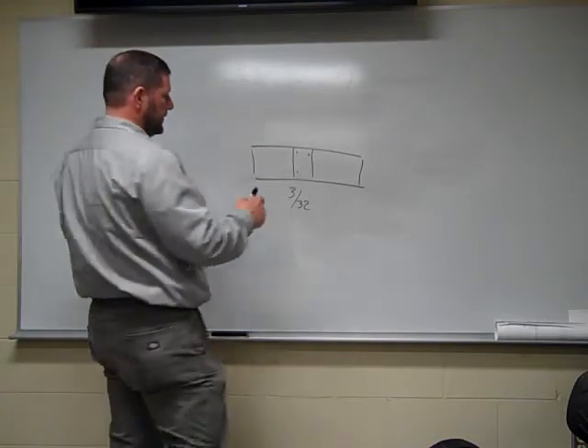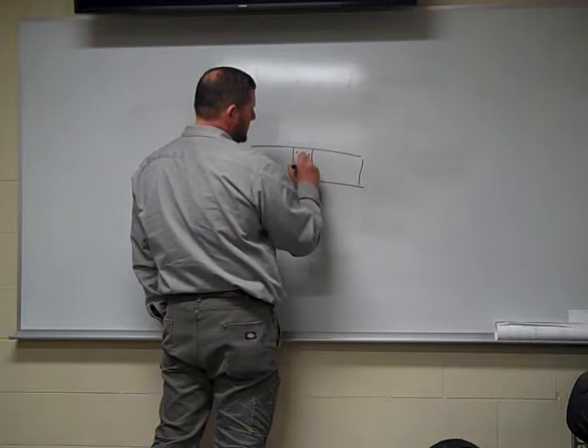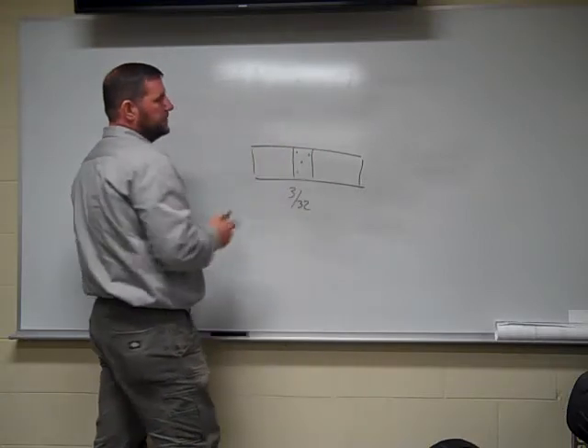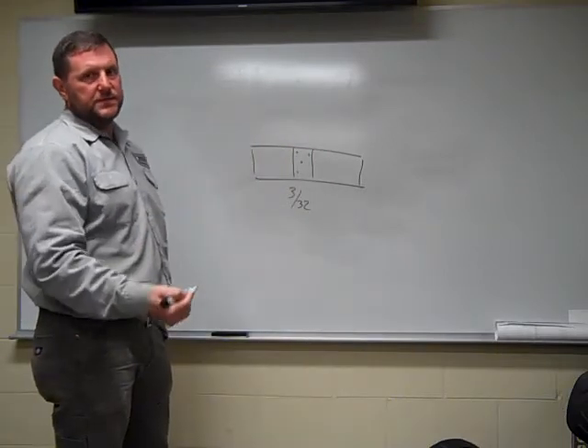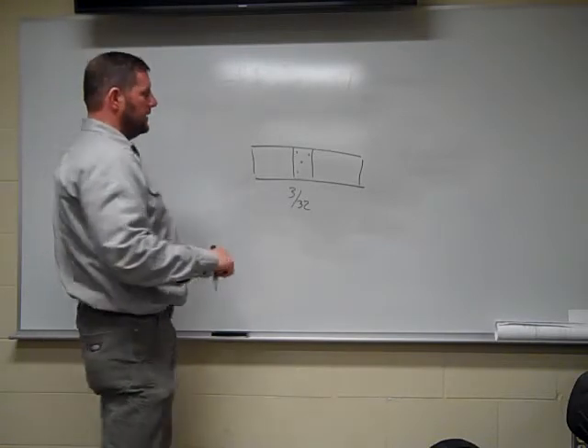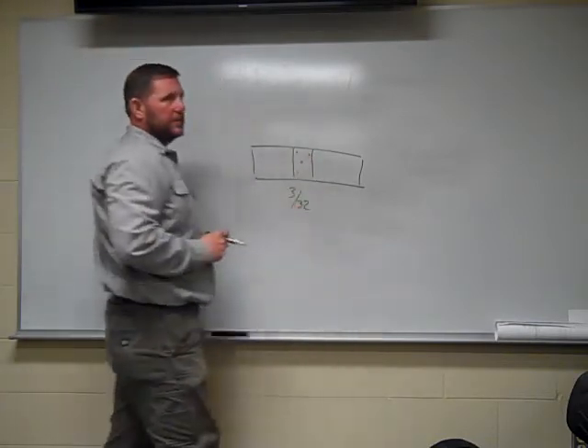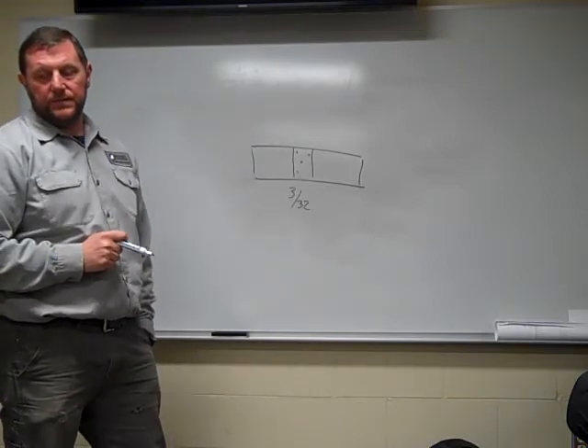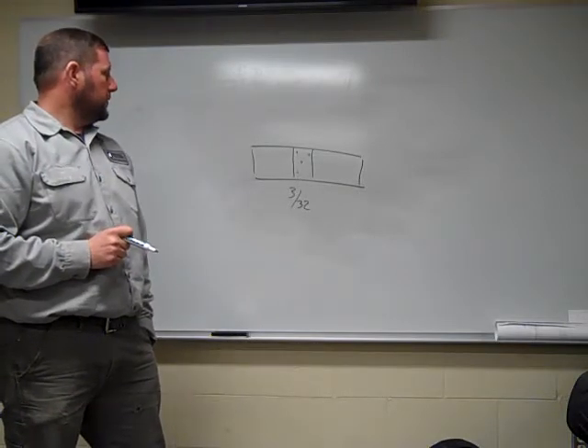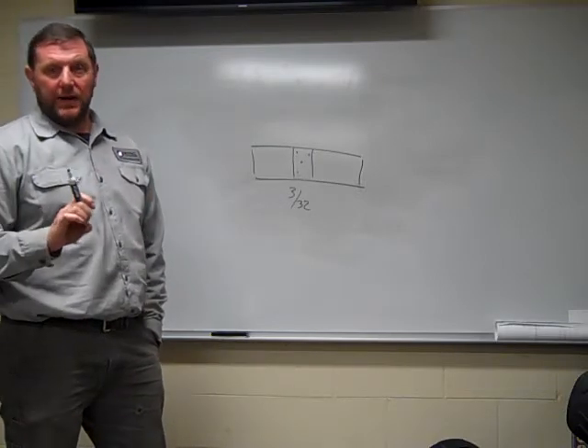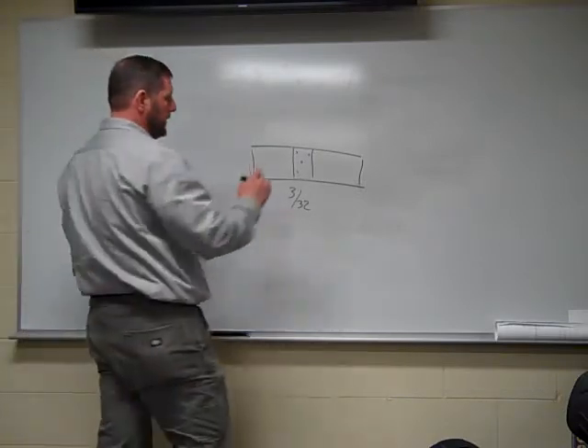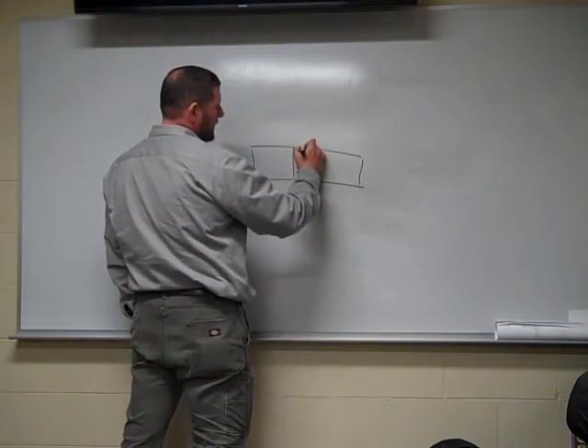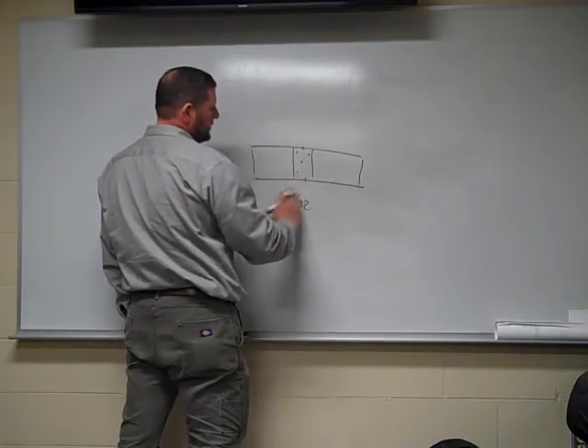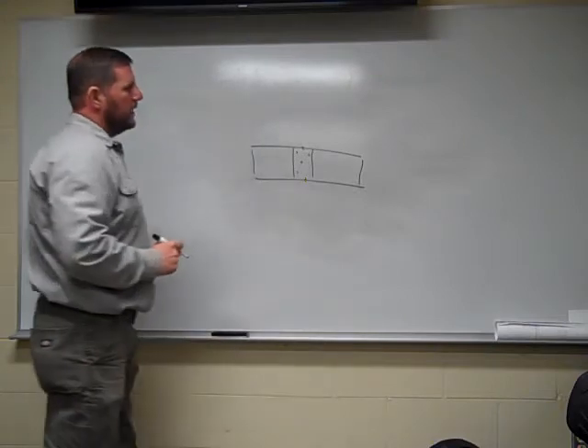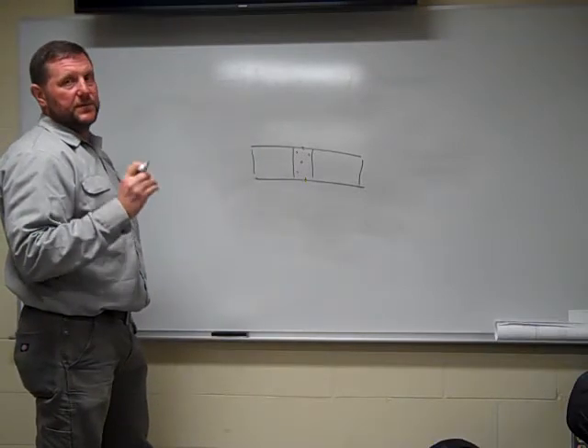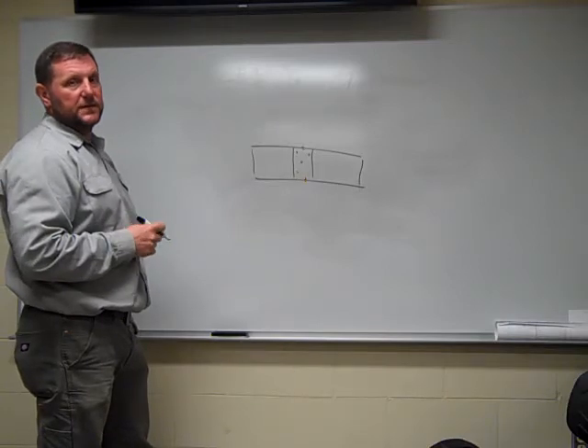And you're allowed up to a total of 3/8 total. So we add all these up. So if I have 4 of them, they add up to more than 3/8, you fail. Keep in mind, none of them can be bigger than 3/32, porosity, and so on. Absolutely no cracks are allowed. You are allowed a linear crack right on the edges up to about a 1/4 inch. The no cracking comes into the visual inspection before we bend it. After it's bent, it's a little different.